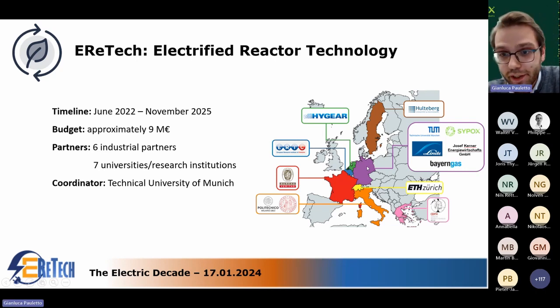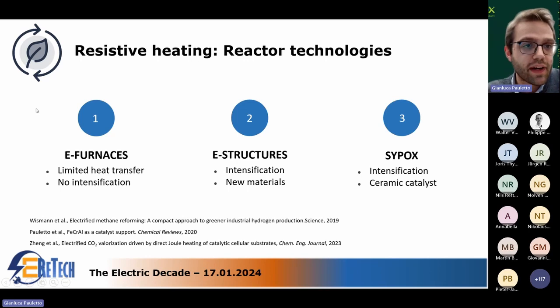I guess we start immediately a bit on the technical side, and as Walter was mentioning before, we are working with resistive heating. If we compare the potential reactor technologies that you can develop using resistive heating, you can mainly identify 3 different options. The first option is simply a furnace, like an oven similar to the one we have at home, just for higher temperature, and you install your reactor inside. So you are generating the heat around the reactor and transferring it through the wall. In this way, you still have a limitation on the heat transfer that you also have in a traditional firebox, and you are not really able to intensify the process.